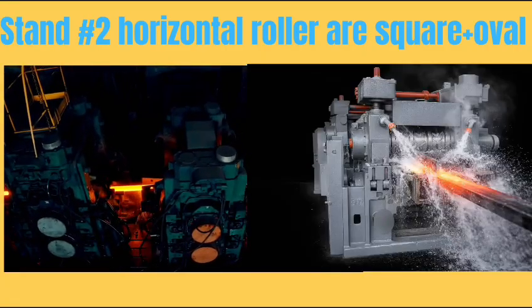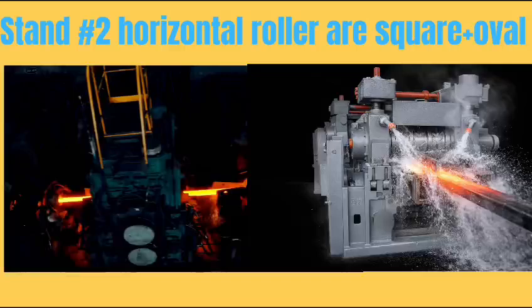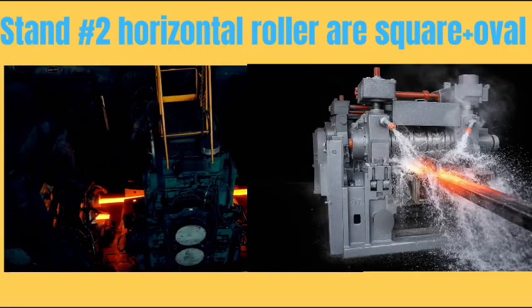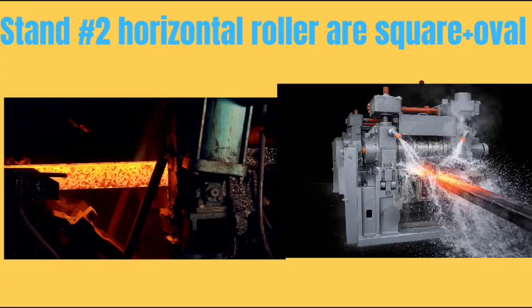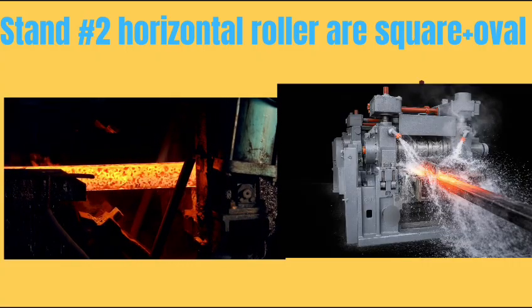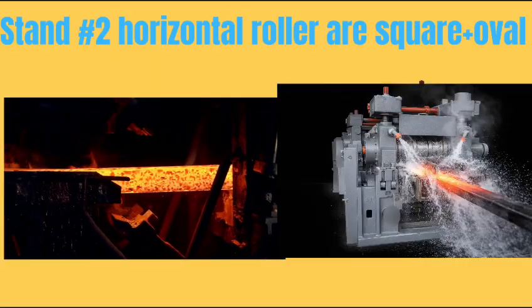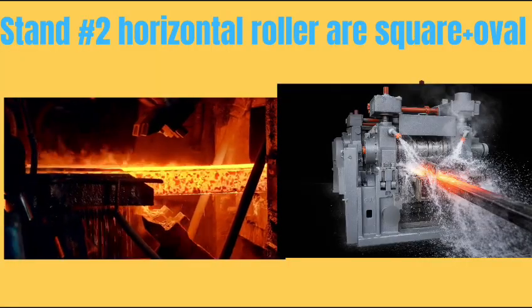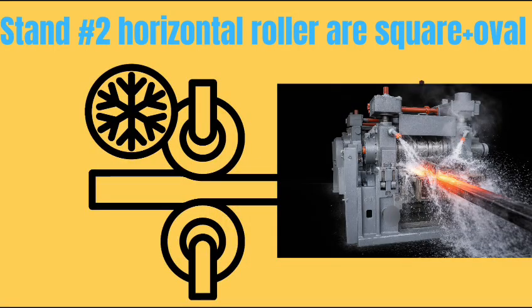Stand number 2, horizontal stand. The billet feeds into the horizontal stand with two horizontal rollers, both rotating in opposite directions. The hot billet passes through the center groove. Because of the rotation, the two rollers grip and pull the billet forward. The billet size reduces from 110 mm to 95 mm, a reduction of 15 mm. Square to oval shape conversion. The billet speed is 6.5 meters per second.